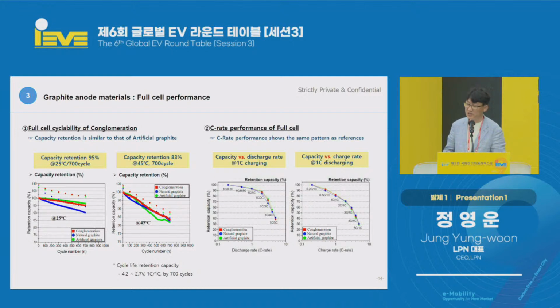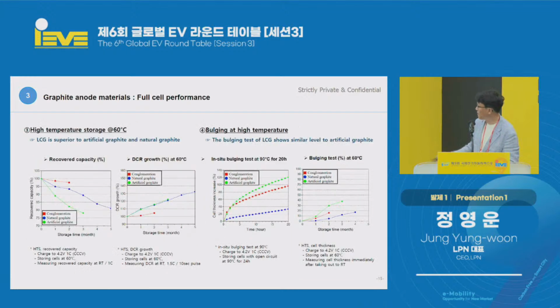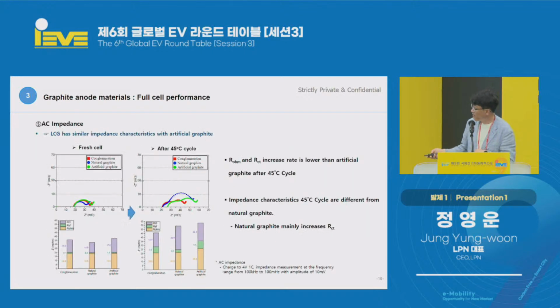And C-rate performance, the pattern is not so obvious, but between the green and red lines, compared to the green line, there's a lot of overlap. So we felt confident that we can replace artificial graphite. And capacity recovery requires 2 months of 60 degrees Celsius storage. This shows 60 degrees, 2 months. And the bulging test was lower. The level was lower than artificial graphite.